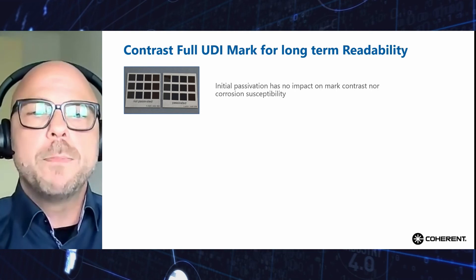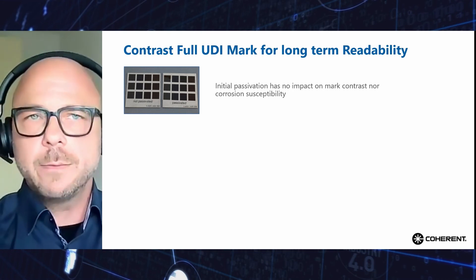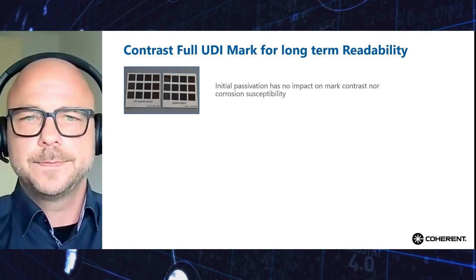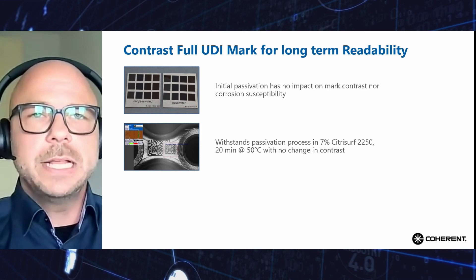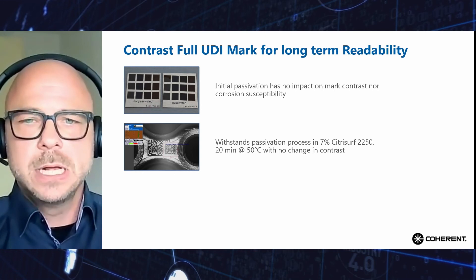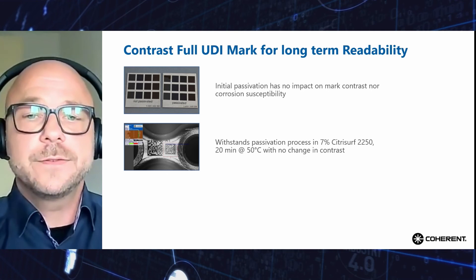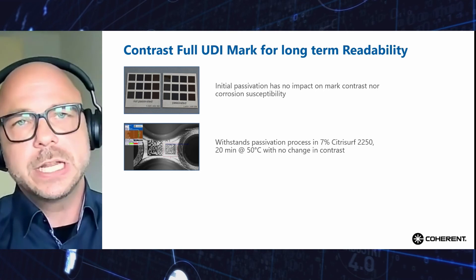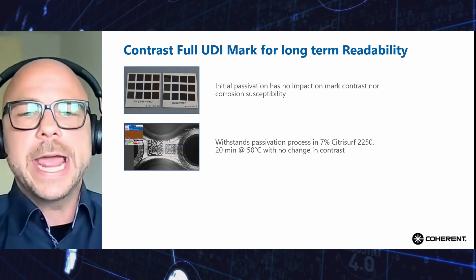Comparing two coupons, we see that regardless of whether passivation occurs before or after the marking, the picosecond laser marking shows no change in color and contrast. A data matrix code clearly and contrastfully marked on the surface goes into a chemical passivation bath at 7% Citrisurf 2250, 20 minutes at 50 degrees, and we see no change in contrast — meaning no fading by the passivation chemical process on the marking result.